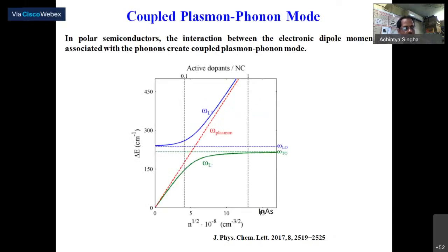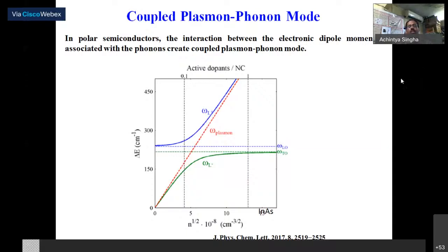Actually, when you have some charge in the system, the field of this plasma will create a plasmon, and the field of the plasmon and the phonon vibration also give you some dipolar effect. This dipolar electric field and the plasmon electric field interact, and they will create a coupled plasmon phonon mode. So we can get the plasmon phonon mode by changing the charge concentration within the system, and we can measure that with Raman spectroscopy. Then in the next slide, I will show you a very nice experiment that we did a few years back. So go next.